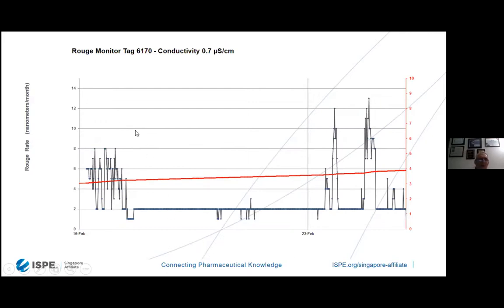So this is a hot water WFI system running at 80 degrees Celsius. And the hot water heater comes on when it goes below 80 degrees C, and it takes it up to 85 degrees C. So when the heater comes on, the rouge rate goes up because of the higher temperature. When the heater goes off, the rouge rate goes down. And when the heater comes back up, it goes back up again. And when the heater goes off, it goes back down.